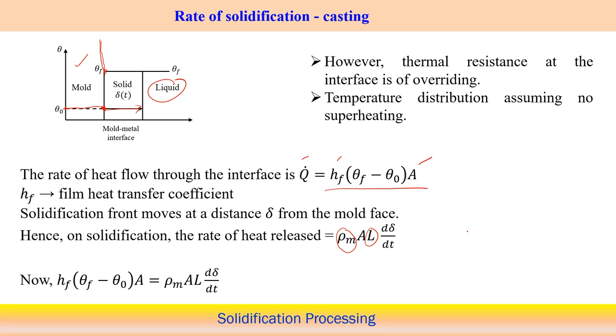released in this case. Here we are considering only the latent heat release, that means the heat of the change of phase only, because we are neglecting the superheating in this particular case. So we are assuming the liquid metal is exactly at the melting point temperature, just changing phase from liquid to solid, and it considers the latent heat only. So this indicates the total amount of heat released to create the delta, when at a particular time the solidification front moves delta T. So it is rho m, A the cross section area, and this is basically the velocity. The cross section area and the velocity give a volume flow rate, and multiplied by the latent heat, that indicates the total amount of heat released over the time t.